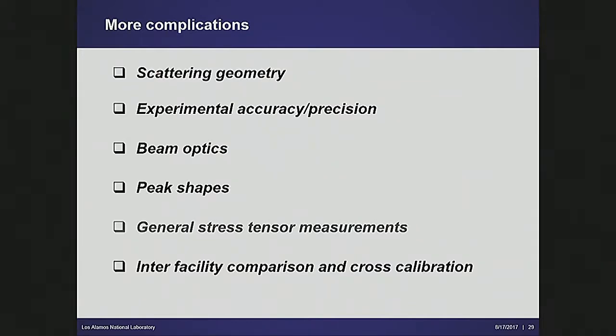The scattering geometry. One of the big issues with stress measurements, if you're doing spatially resolved, is if the sampling volume comes out close to the surface, and so instead of being fully immersed, it's only half in and half out. What that does is introduce artifact peak shifts that can also affect the results. Then there are beam optics and peak shapes.